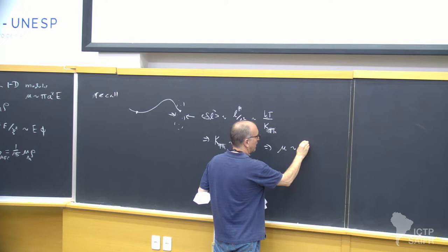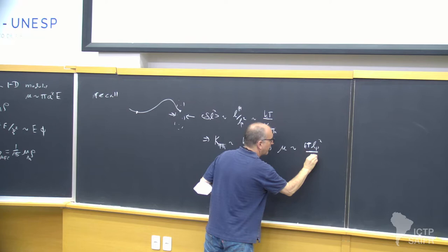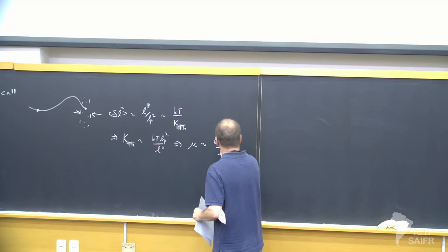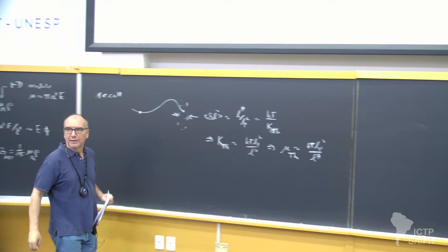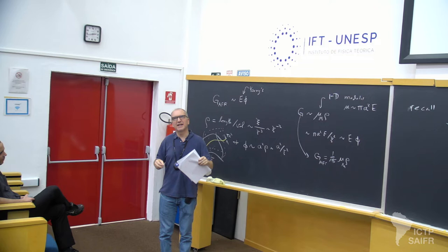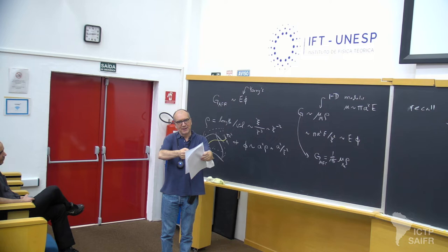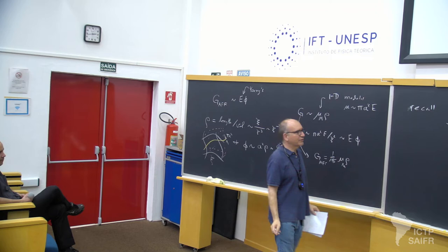To turn this into a spring constant: solving for it, I get kT LP squared over L to the fourth. The Young's modulus corresponding to that would be kT LP squared over L to the third — just one power of length different. If I plug that into the modulus expression, I'll call this a thermal Young's modulus, taking into account those thermal fluctuations. It's sort of like entropic elasticity — by pulling on it, you're reducing its available fluctuations, and it responds with an increasing force. There's a Hookean regime with that kind of behavior.